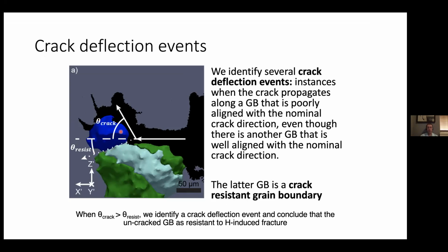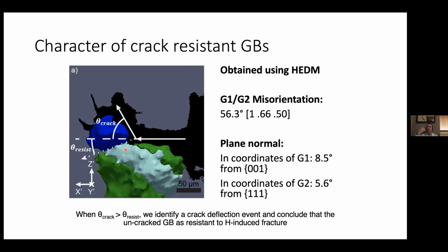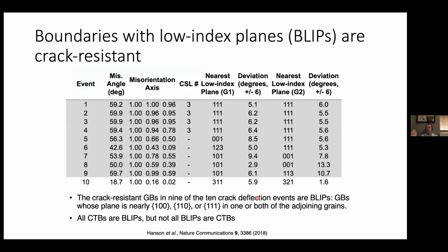And of course, because the reconstruction that we have here provides us with both the shapes and locations of the grains, as well as their crystallographic orientations in space, we can actually back out the complete 5-dimensional crystallographic character of this boundary. So this particular boundary, for instance, has a misorientation that can be described with this angle-axis pair. And it has grain boundary plane orientations that can be written down using Miller indices in coordinate frames fixed in the two neighboring grains. So in one of the two grains, the facet plane is a 001 type plane, and in the other grain, the facet plane is a 111 type plane. Okay, so we get the full crystallographic character. We found 10 such crack deflection events in that particular study and on that particular sample.